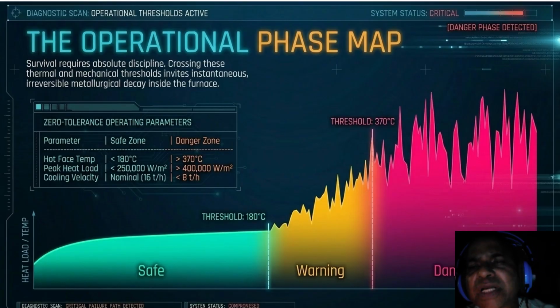If your hot face temperature exceeds 370 degrees, your peak heat load tops 4 lakh watts per square meter, or your cooling velocity drops below 8 tons per hour, you are inviting irreversible metallurgical decay. You can see the danger phase detected alert at the top right. At this point, the damage is done. To stay in the green, we need more than just better software. We need a mechanical upgrade to the stave itself. So we must move from deforming soft copper to a rigid engineered solution that can handle these loads.